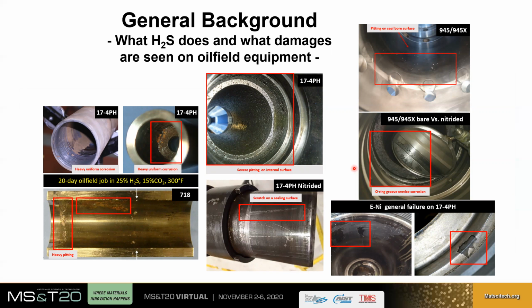Before I go into those details, let me show you through a couple of pictures what hydrogen sulfide does to the equipment and what kind of damage we typically see on our equipment. If we look towards the left, you have here 3 pictures, stainless steel 17-4 pH and a nickel chrome body or Inconel 718. What we see after only 20 days of exposure in the job is quite a bit of corrosion. You can see some pitting and perhaps crevice corrosion on the Inconel 718, and some heavy corrosion elsewhere on the stainless steel.